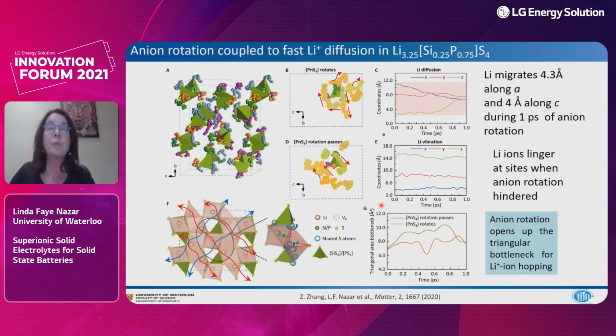So the reason how this physical coupling actually works is that this shows the diagram of the lattice, this shows the pathways for lithium ion transport, and effectively we then blow up one of these little regions. You can see that the lithium pathway that goes from a tetrahedral to an octahedral environment is such that both edges are spanned by a PS4 group. And so as this PS4 group rotates, because of anion dynamics, it actually opens up these triangular windows for transport.